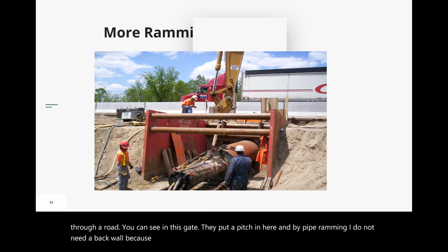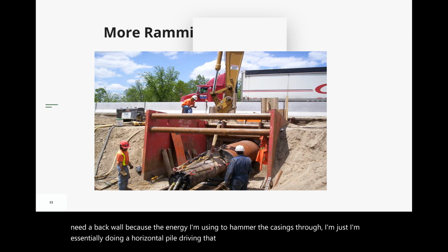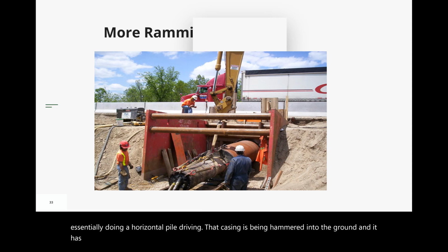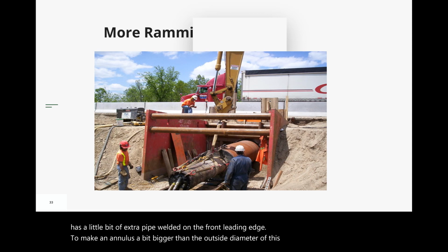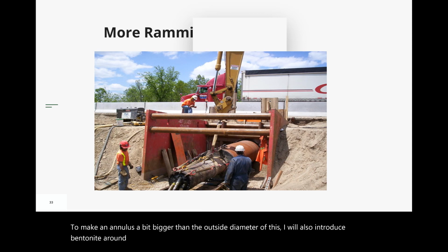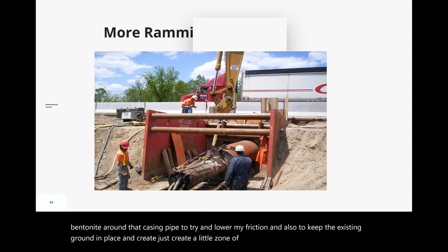I will also introduce bentonite around that casing pipe to try and lower my friction, and also to keep the existing ground in place, and create a little zone of low friction area to allow my casing pipe to advance as far as possible. And as I do ram in, of course, I'm building up weight on the inside because I'm encapsulating the material that was there in the ground originally inside the pipe. I will get to the point where my weight has come up because of that material. So I may stop, take off the hammers, take the whole thing apart, go in, clean out the material that's inside the casing pipe, reattach the hammers, and start going again.